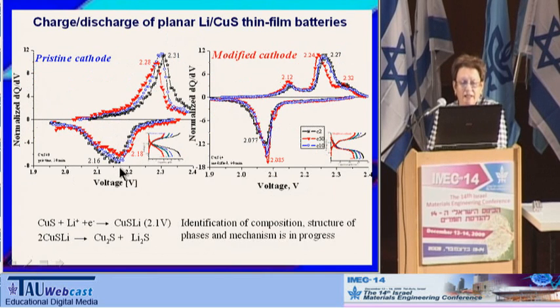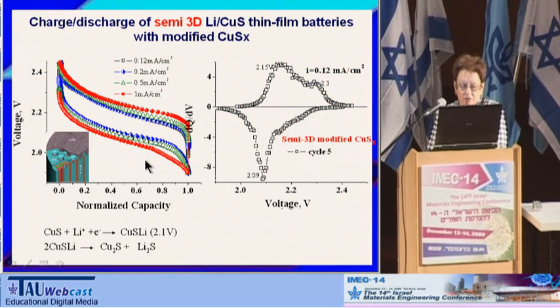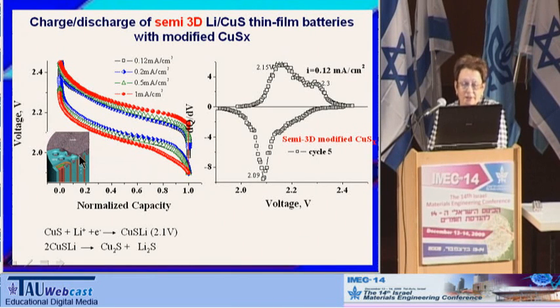Furthermore, on prolonged cycling, there is a broadening of the dQ over dV peaks of the planar cell with pristine cathode. This raised the possibility that some disordering may occur in the system on prolonged cycling. The opposite is true for the cell comprising modified cathode. At low current densities, the charge discharge curves of the semi-three-dimensional cell with modified copper sulfide cathode are relatively flat. The sloping character of the curves at high discharge current is caused by overvoltage, which in turn we relate to the high internal resistance of the semi-three-dimensional microbattery, in which the anode is applied only to the upper part of the battery and is absent inside the channels.